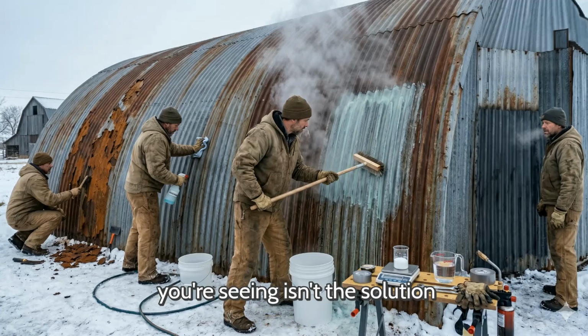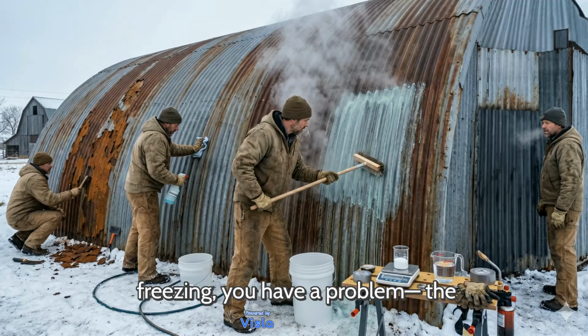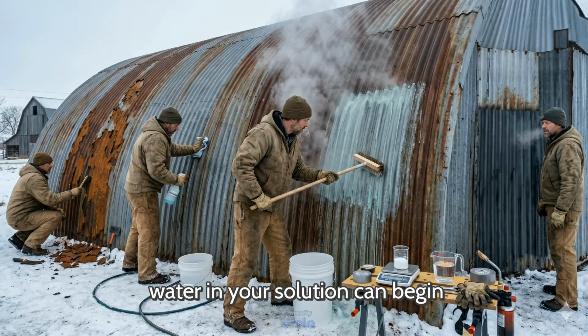The steam you're seeing isn't the solution boiling. It's the exothermic reaction generating heat as the acid attacks the rust, and in cold air that heat differential creates visible vapor. It's actually a sign the chemistry is working aggressively. Cold application does require one important adjustment. The solution needs to stay liquid on the surface long enough to complete the reaction. If the surface temperature is below freezing, you have a problem. The water in your solution can begin to freeze before the conversion finishes.